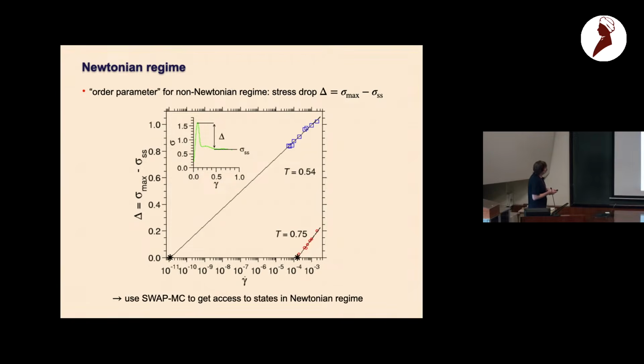And we can measure this: the distance from the maximum to the steady state stress, this is some value of delta. If this delta disappears, we reach strain rates, and below these strain or shear rates, we can expect that we obtain a Newtonian response.